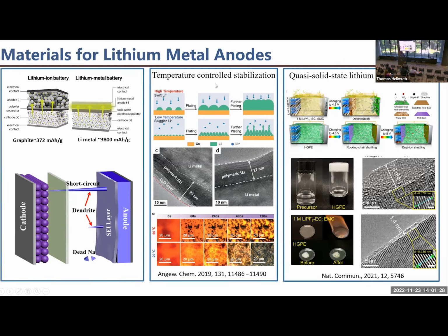One is the temperature controlled stabilization of lithium metal anode, and the other one is using a polymer additive in the electrolyte to stabilize the interface both on anode and cathode. So for the first one, we found that if we use high temperature for testing, for example, 70 or 80 degrees centigrade, only the temperature is a sufficient factor to stabilize the reversible stripping and plating. We don't need anything else.